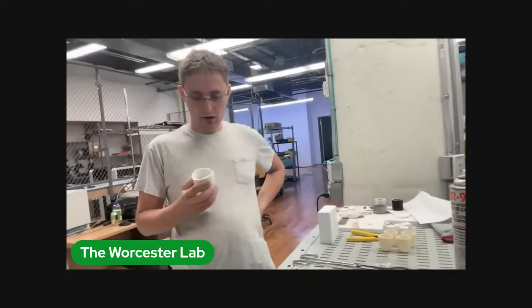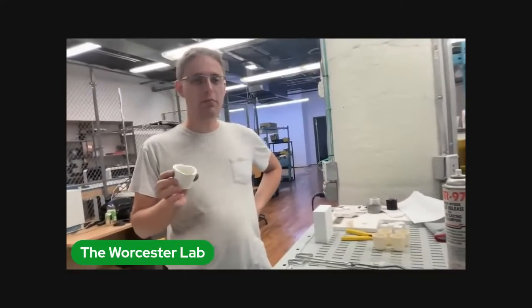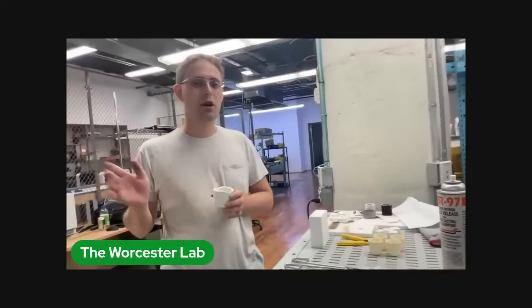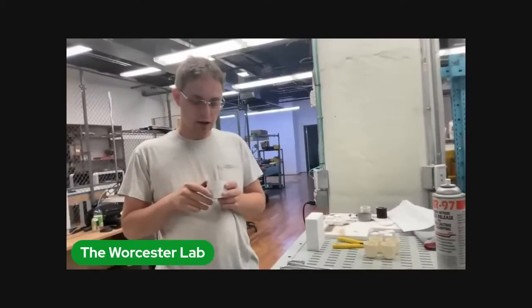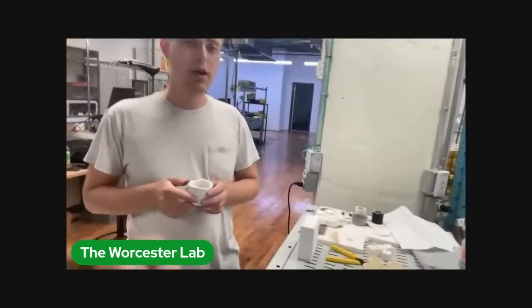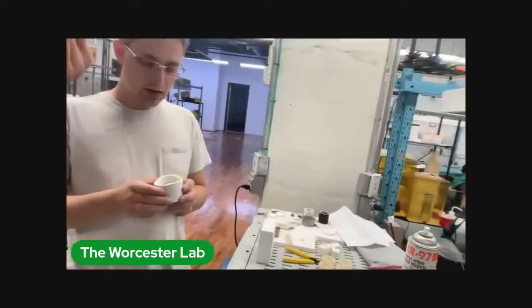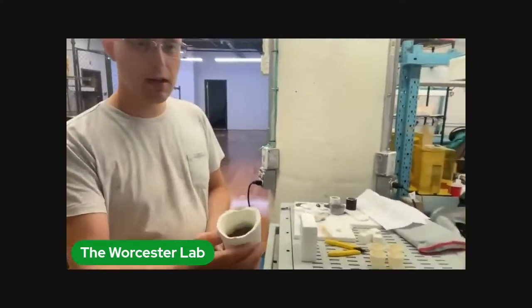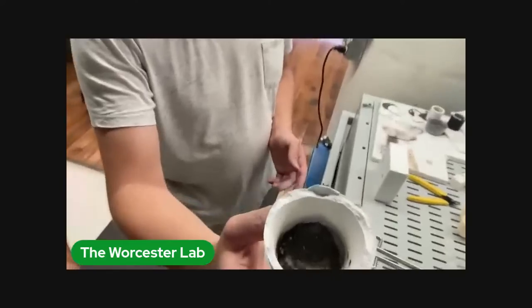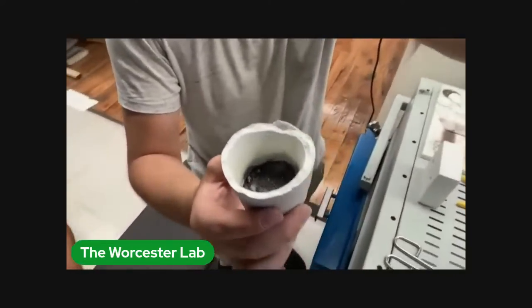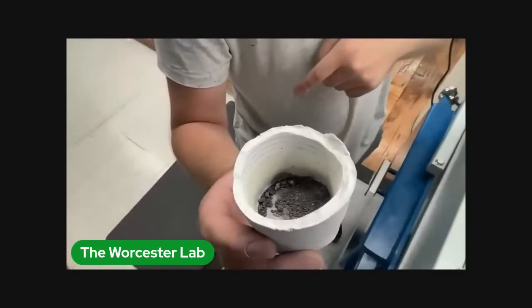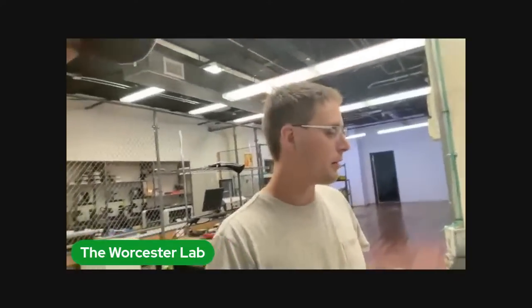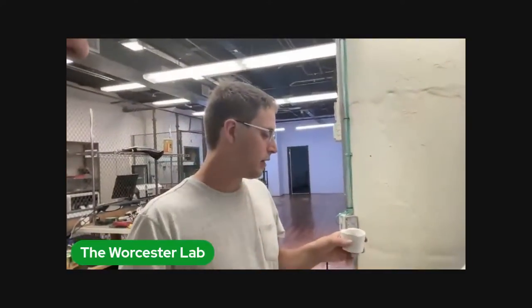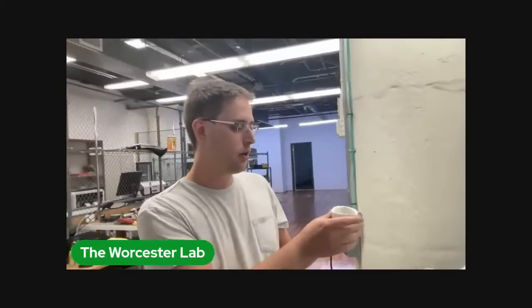purportedly. So there's just a little bit of phosphorus in there. There's way too much copper, so they're going to have excess copper, and there's way too much lead as well. So it seems like these crucibles, due to the yellow coloration of the walls, the lead probably soaked into the pores on these alumina crucibles.